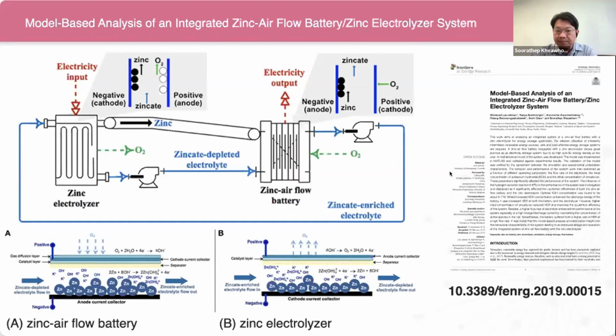For the overall integrated system, it was observed that the current efficiency was dominated by the electrolyzer. Therefore, increasing zinc cation concentration and the electrolyte flow rate had a beneficial effect on the current efficiency of the integrated system. On the other hand, the energy efficiency of the integrated system was essentially influenced by the discharging cell. Maximum energy efficiency was obtained at the optimum concentration of potassium hydroxide. Overall, it was found that the hydrogen evolution reaction had a detrimental effect on the performance of the integrated system.